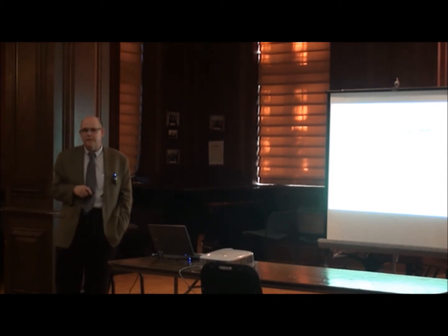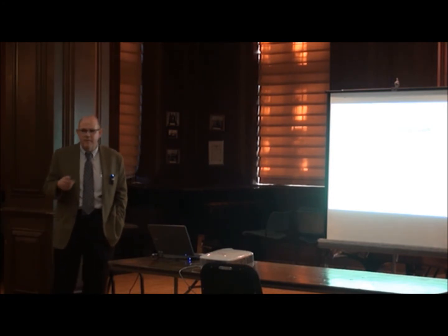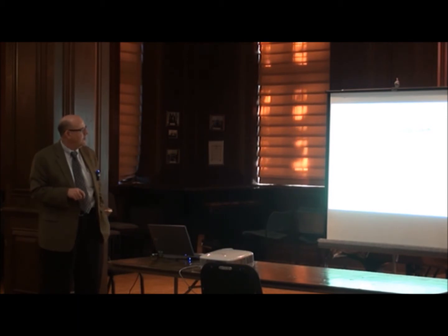This is actually the very smooth surfaces sliding against each other, okay? In the case here, where you see the friction coefficient growing, this is a very rough surface sliding against a smooth surface. It's deforming, plastically deforming, maybe digging in, compressing, increasing the real area of contact. And then for some optimum surface roughness, the friction coefficient was minimal, and it stayed pretty constant.